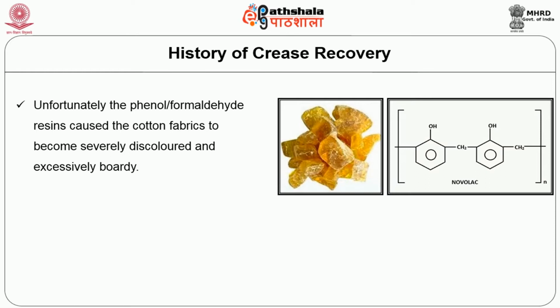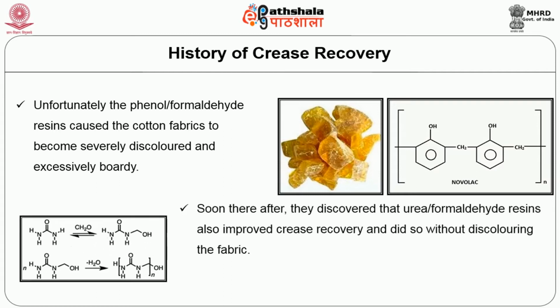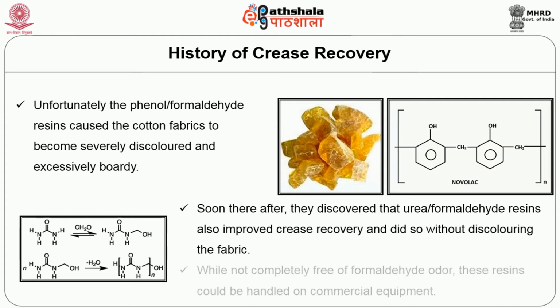Unfortunately, the phenol formaldehyde resins caused the cotton fabric to become severely discolored and excessively boardy. Soon thereafter, they discovered that urea formaldehyde resins also improved crease recovery and did so without discoloring the fabric. While not completely free of formaldehyde odor, these resins could be handled on commercial equipment.